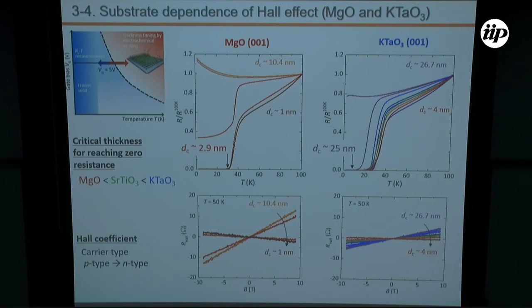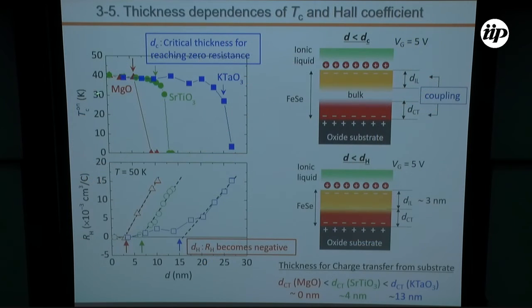But here we note that the critical thickness for the superconducting transition is smaller for MgO, and larger for potassium tantalate. This can be very clearly seen by plotting the onset temperature and the Hall coefficient as a function of the thickness.